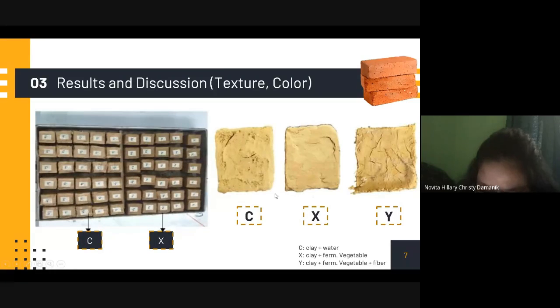The cracks here occurred in the 3rd week of curing. The cracks occurred only at the bottom of the samples and mostly occurred in C and X. The Y with sugarcane fiber had small cavities due to the existence of short fiber. For further research, the use of more refined fiber is suggested to see if it would still create small cavities. The overall texture of samples without sugarcane fiber was bumpy and not as smooth as expected, due to an extremely clayey mixture.